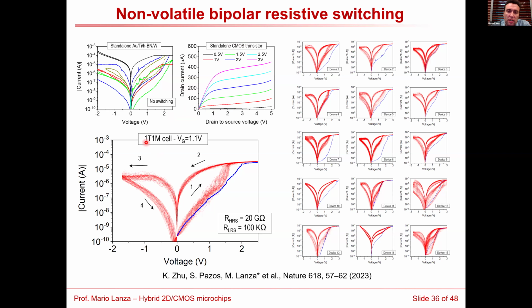And then we measure the one transistor, one memristor cell with gate voltage 1.1 volt. And then we observe that during the first IV curve, which is the blue one here, the current increases. And during the back ramp, we observe that there is an increase of current for the same voltage. So the resistance has changed.